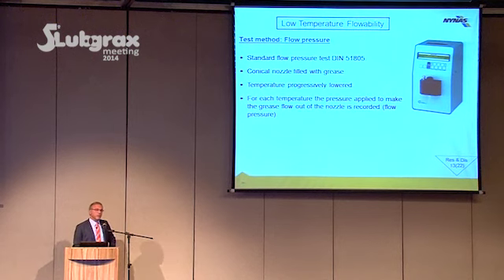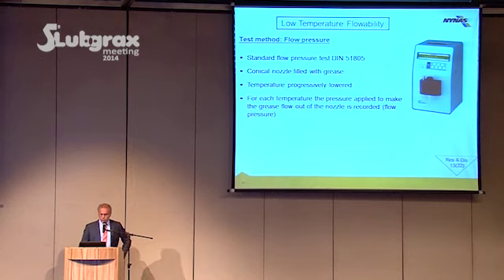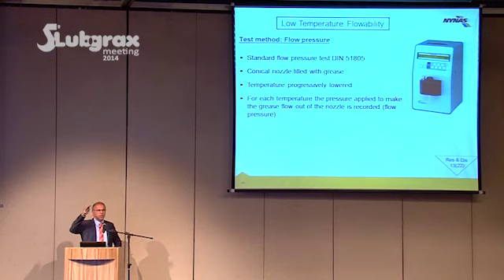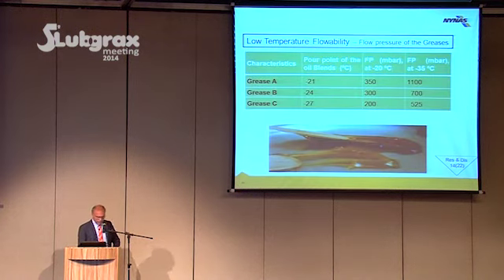Low temperature maybe is not an issue here in Brazil, but in mining it is an issue. One standard test which you can use in the laboratory in order to simulate this is a German test method called flow pressure. I won't go through it. What you do is you apply a small amount of grease, you temper it, and then you measure how much pressure you need in order to push it through the nozzle. So we have done it at minus 20 and minus 35 degrees C.